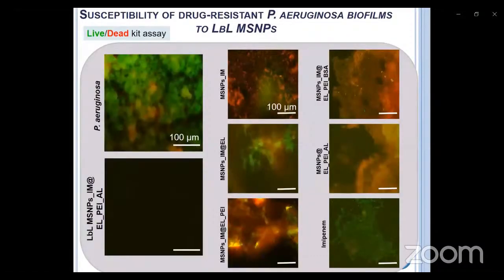Similar results we can see from the live dead kit assay. We saw that established biofilm was resistant to the antibiotic solution. Only the layer-by-layer mesoporous silica nanoparticles with alginate layers showed strong biofilm elimination properties.